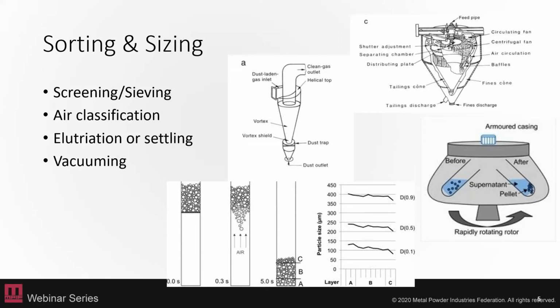Another settling method that I've used for nanoparticles is centrifugation, and that's shown on the right here, where you're using a centrifuge to pull down powders that are dispersed in a fluid. And actually the time that you're centrifuging and the speed that you're centrifuging at, you can change those, and those will cause you to get a different size powder that's pulled out of the fluid. So you can monitor and select different size fractions by monitoring your centrifuge parameters. So these are some of the top level sorting and sizing.